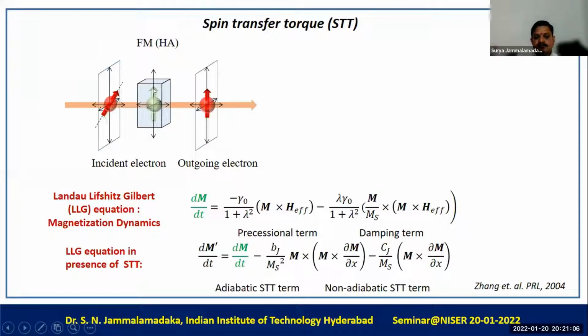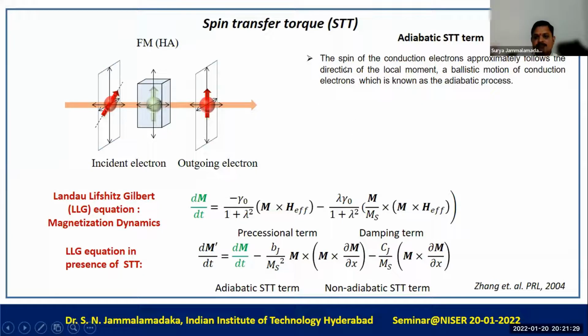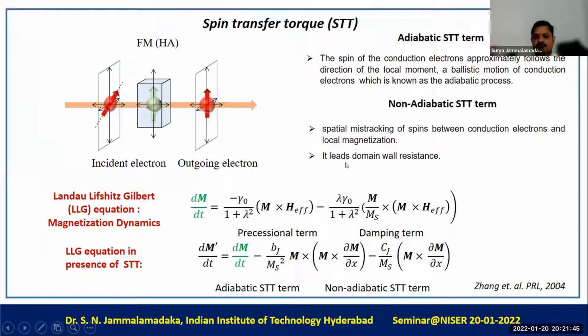Now, if you introduce the concept of the spin transfer torque and look at the Landau-Lifshitz-Gilbert equation, in addition to the precessional term and the damping term, we'll also have two more important parts. One is the adiabatic spin transfer torque term, and another one is the non-adiabatic spin transfer torque term. In the adiabatic spin transfer torque, the spin of the conduction electron will follow the local magnetic moment. Whereas in the non-adiabatic spin transfer torque, the spin of the conduction electron will not follow the local magnetic moment direction, which leads to domain wall resistance. In the spin transfer torque bias phenomenon that I'm going to explain, we use this non-adiabatic spin transfer torque term and try to explain the phenomenon in an infinitely long ferromagnetic nanowire.